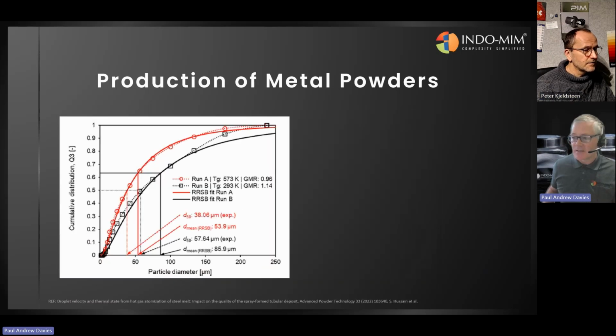And similar work has been done also here, increasing the gas temperature from 293 Kelvin up to 573, and then the median particle dropped from 53.9 microns down to 38.06 microns. And the gas to metal ratio, is that on weight or is it on volume? Good question. I'd have to read this paper here, but it's usually volume, I would have thought, because it seems that you get a better yield with less gas consumption.